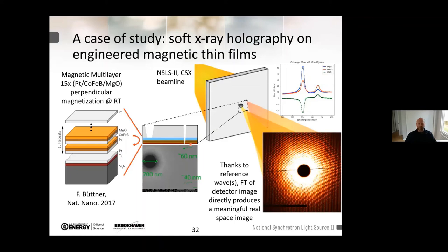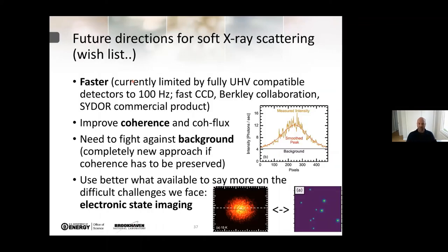And exploiting the knowledge of our German collaborators, we produced masks for holography with a well-controlled dimension, exposing the sample and a couple of references, all of fixed and very controlled diameter, such that using this XMCD, because we have a perpendicular magnetization in the field, and the holography setup, as I said, and using our coherent beam, we can get beautiful images that can be inverted as a holography image can be, given that you propagate information on that, so it is very relevant. Also because it can extract smaller signal out of the background, so it is really, really relevant.